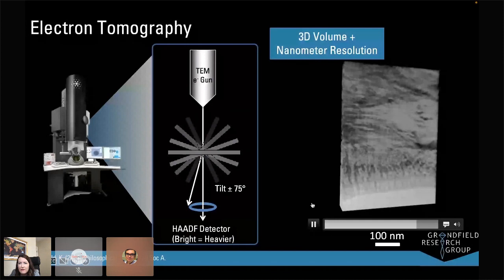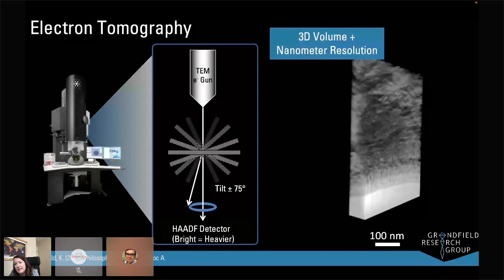And now what we achieve is a 3D structure of our bone implant interface that has nanometer resolution. So we can more clearly see these collagen fibrils and how they move across and interact with the implant zone at the interface here.